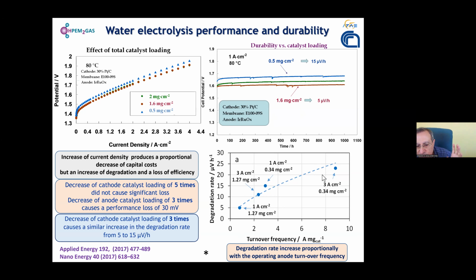We have observed a relationship between degradation rate and turnover frequency. Turnover frequency is linked to the operating current density and to the reciprocal of catalyst loading. So if we decrease catalyst loading and increase current density, we have higher degradation rate. This means there is still a long way to go to develop stable and highly performing electrocatalysts.